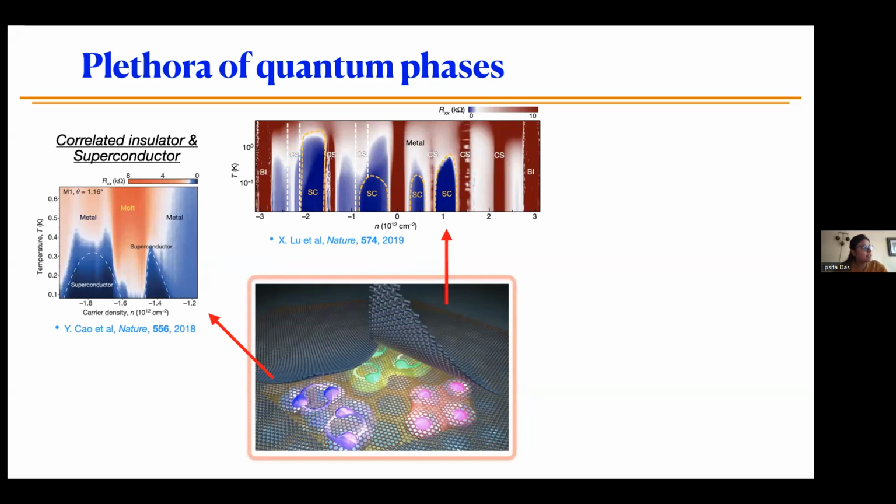So microscopically this can happen. The main problem is that 1.1 degree is not very stable. And also when we do this micro manipulation, we have a mechanical rotational stage, and we do all these rotations, but microscopically we don't have full control on how they are actually touching each other, because the stacking process is sometimes a bit complicated.